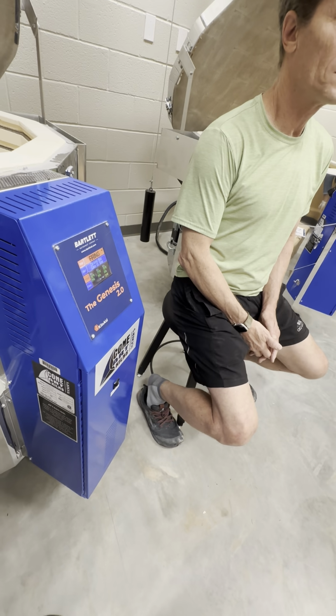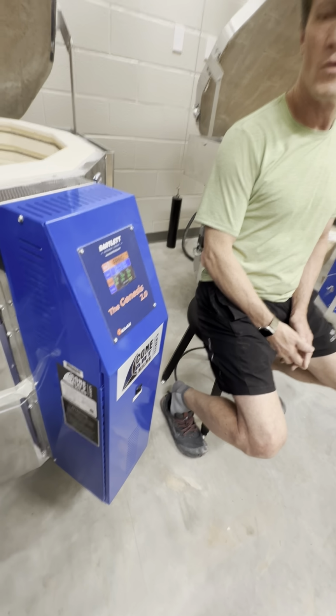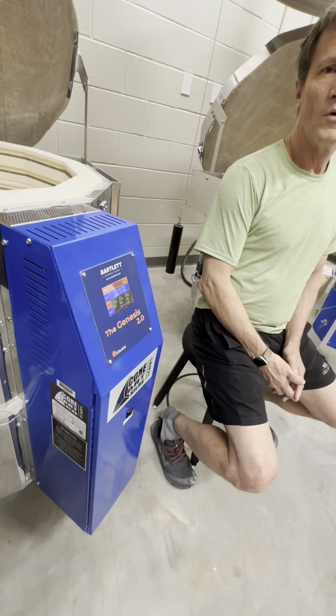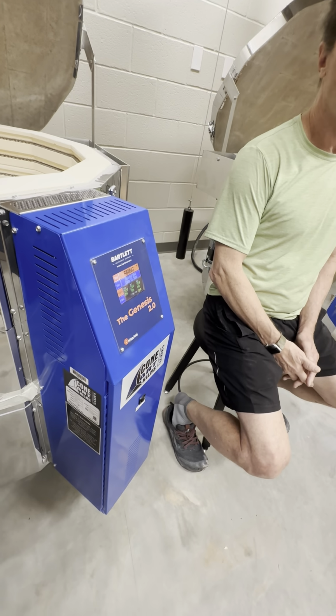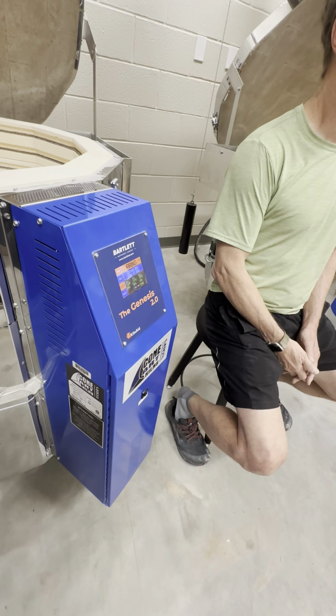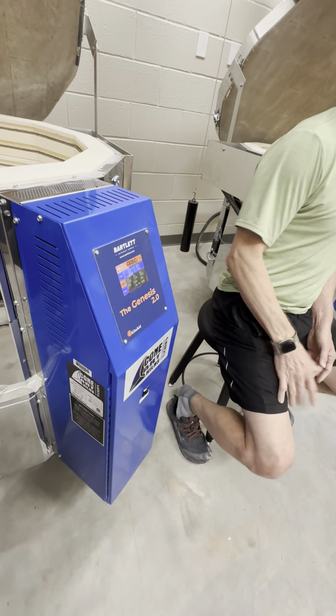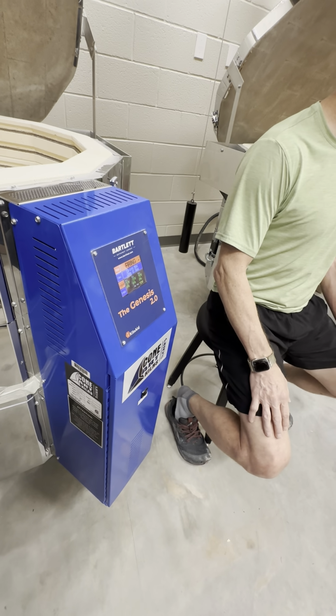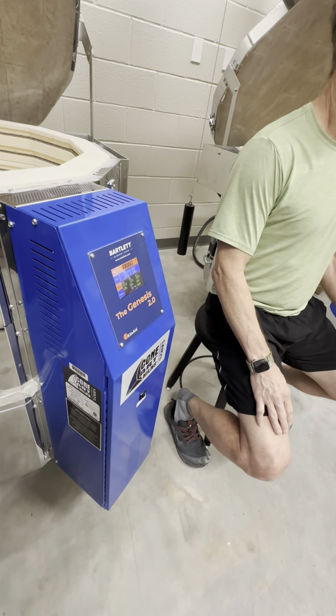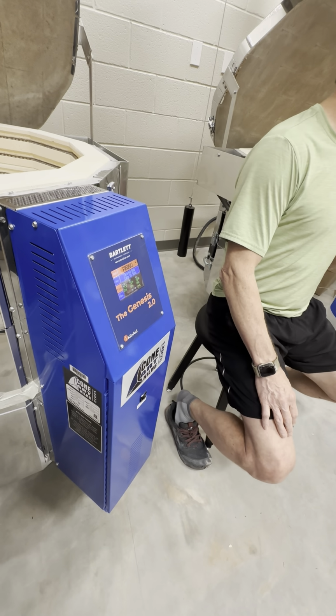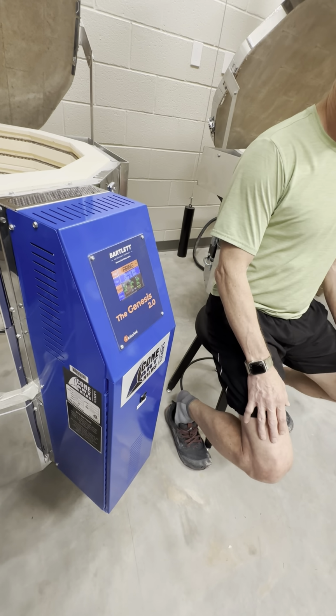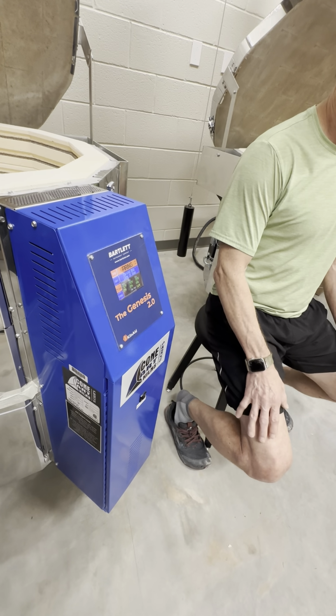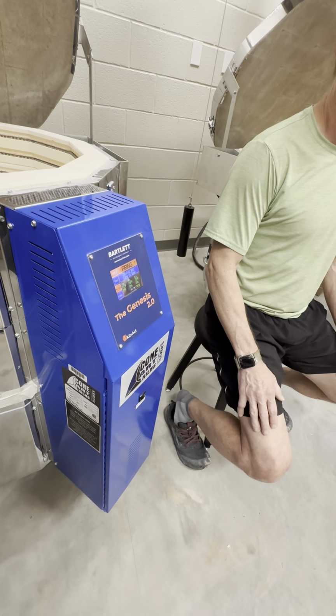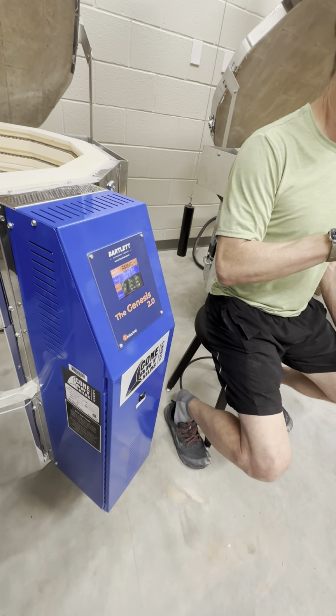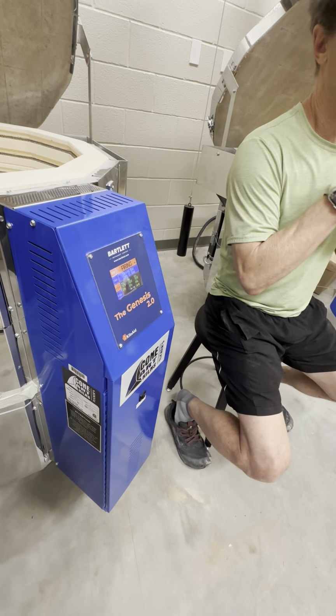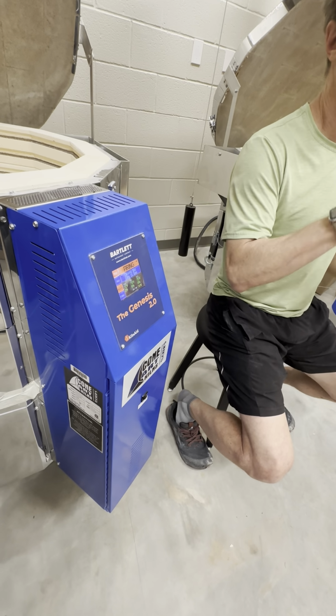Other questions? Does the preheat and the slow do the same thing? You're doing the preheat and the slow to make sure that everything's nice and dry. The preheat is going to keep it at less than 210 degrees. That's a great question, okay? Hotter than 210, it's going to boil, and steam's going to be given off if there's any moisture. So the preheat is just to get that physical water to go away. The slow is to make the chemical water that's combined with the clay release slowly enough, if you have bigger or thicker pieces.